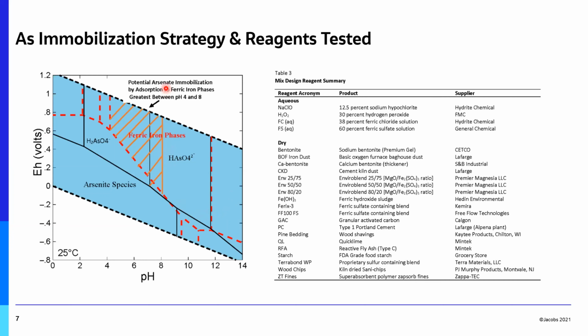So when we superimposed iron speciation on top of this, what we realized is that we needed to be in this crosshatch region to immobilize the arsenic for our site considerations, which meant that we needed to be oxidized and we needed to be between pH 4 and 8. Usually when you're working with a stabilization solidification system and you're adding cement, you're way over here in the pH 12 and a half to start the reactions. And for long-term stability, for most projects, you want to make sure that your pH is maintained above 10. That wasn't going to work on this project.